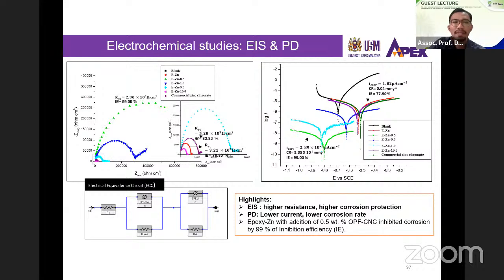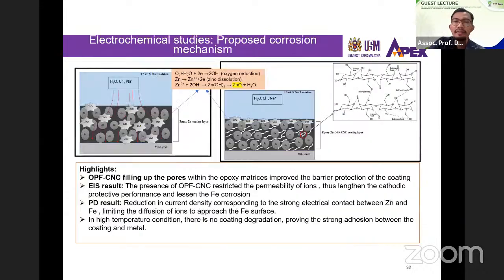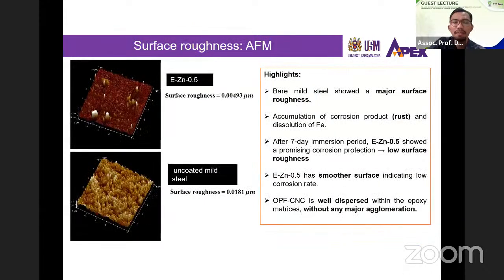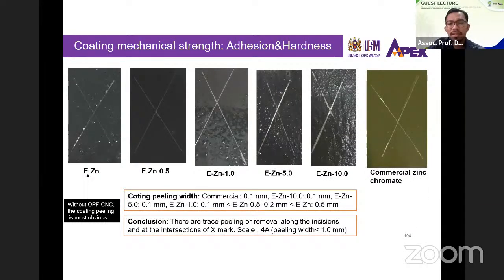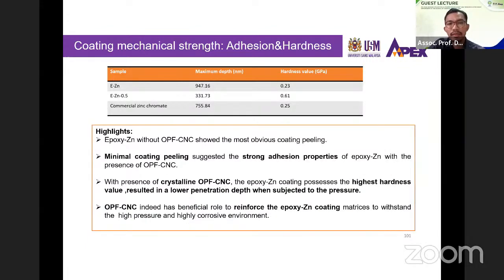For electrochemical studies, we obtain slightly better properties in terms of corrosion resistance, and even the surface roughness of the coated sample is better. I mean, in terms of the smoothness in comparison with the uncoated or coated samples. Some other testing includes adhesion and also hardness tests. We did the salt spray test for aging, and obviously from here we see that 0.5% of CNC introduced in the epoxy coating is better in terms of the aging test. And even for the hardness test, 0.5% of CNC blended with epoxy coating produces a slightly higher hardness.